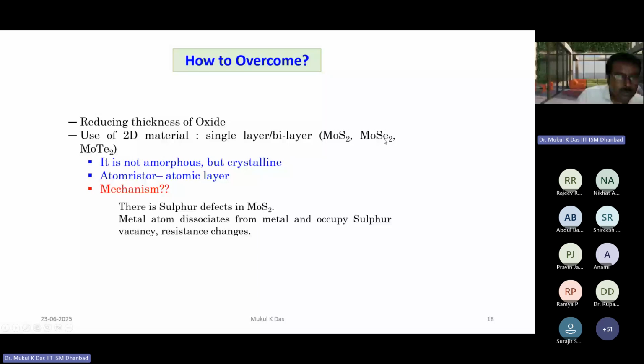What is the technical difference? The 2D materials we are talking about are not amorphous. That means it is not a fully stochastic process you have to go through, but a crystalline one. The layer thickness is on the order of atomic dimension, which is why it is sometimes called an Atomristor, or atomic layer. The mechanism is a bit different from nanoionic film formation. MoS2 is a very well-known material, and in MoS2 there are some sulfur defects. Sulfur defects means the desired molecular arrangement of molybdenum and sulfur is missing in some developed MoS2 films. These sulfur defects can be engineered to change the resistance of the MoS2 layer.